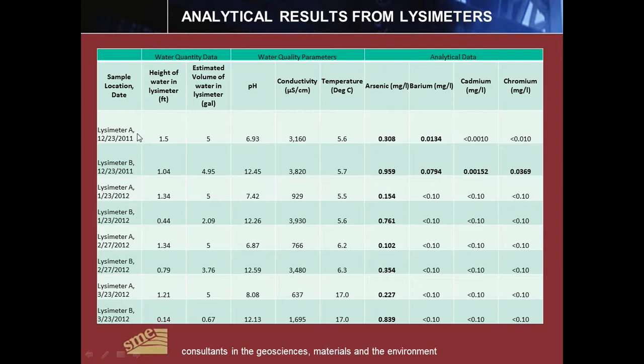Lysimeter A, as I mentioned earlier, is under the limestone, and lysimeter B is beneath the blended materials. You see that initially we had some readings in all of our heavy metals on the first go-around of sampling. But after the second sampling, the barium, cadmium, and chromium numbers all dropped down to non-detect limits, but the arsenic levels still remained high. It should be mentioned that in Ohio arsenic is a naturally occurring background material in our soils and groundwater. So it's pretty typical to see arsenic show up in places that normally a person wouldn't think you'd see it. Studies by the University of Wisconsin on recycled concrete aggregates compared to natural aggregates show the same trend of readings.